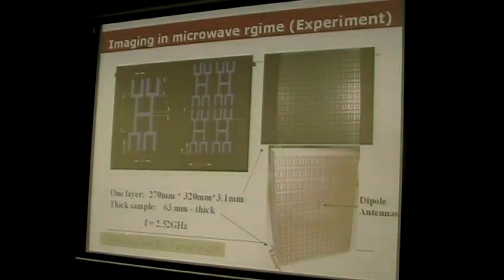Now we change to the microwave frequency region to perform the imaging experiment. The experiment was done by Professor Zhang's group at Zhejiang University. The structure is slightly different from the ideal fractal structure. The structure details are shown here. We work at the resonance frequency, which is the plasma frequency of this structure. We put an antenna working here, and then we put another antenna on the back of this lens to measure the field distribution. This is basically what the experiment has done.